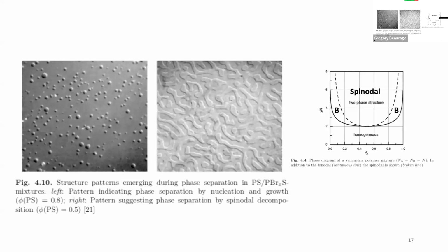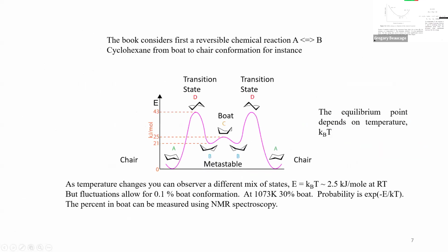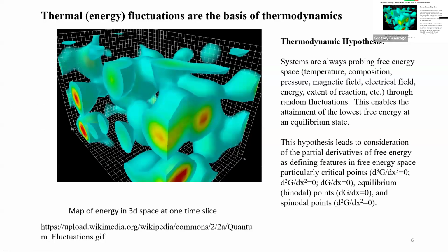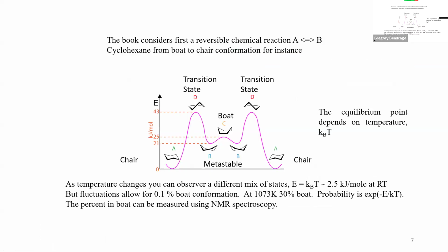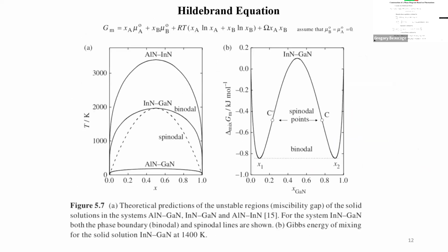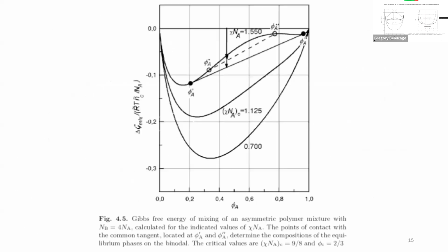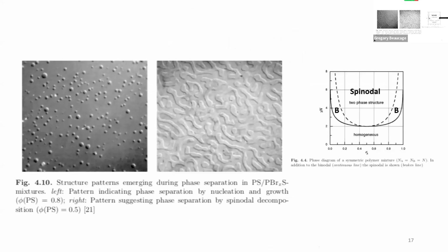In metals you can't easily see this. What happens in spinodal decomposition is that it phase separates along the lines of this thermal mapping and it just becomes solid. In other words, the thermal fluctuations become composition fluctuations. That gets frozen in and grows once you get into the central part of the phase diagram, where you get spontaneous decomposition. You get phase separation automatically without nucleation sites, following exactly the tracing of that.